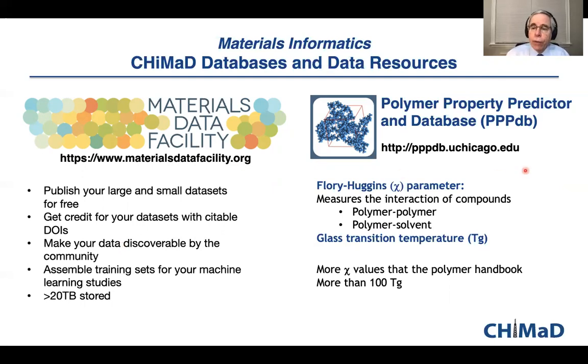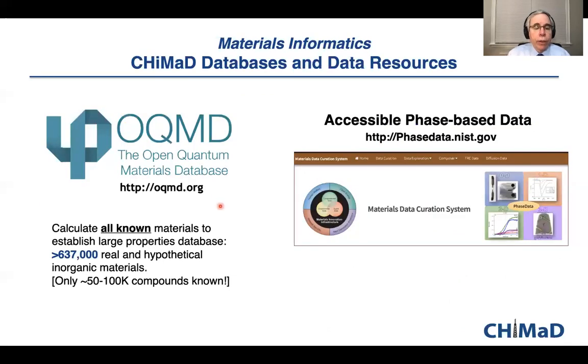Another important database for the soft materials area to enable soft materials design is one in which we're looking at the thermodynamic properties of polymer blends through the Flory-Huggins parameters or glass transition temperatures. And there are now more chi parameters in the database than in the polymer handbook. And we're using natural language processing to help extract these Flory-Huggins parameters from existing literature. The Open Quantum Materials Database uses density functional theory to calculate properties of materials, both hypothetical and real.